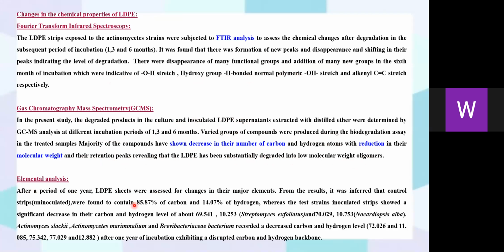Elemental analysis. After a period of 1 year, LDPE sheets were assessed. From the result, it was inferred that control strips were found to contain 85.87% of carbon, whereas test strains showed a significant decrease in their carbon and hydrogen levels of 69.5, 10.25, etc. This was followed by Nocardiopsis alba, Actinomyces slackii, Actinomyces marimmalium, and Brevibacteriaceae bacterium, which recorded a decreased carbon and hydrogen after 1 year of incubation.